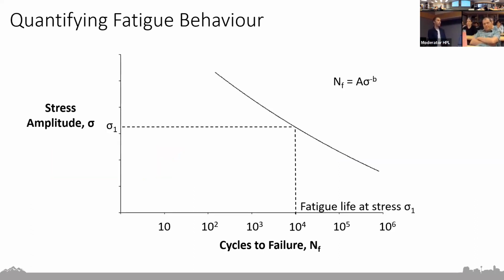So there's been a little bit of previous work trying to quantify the mechanical fatigue behavior of the subchondral bone through some ex vivo mechanical testing. And like some other materials and other bone samples, we typically represent this using what we call a stress-life plot, where we have our stress amplitude plotted on the vertical axis, and our fatigue life, which we define as the number of loading cycles a material can withstand before failure, plotted on the horizontal axis.